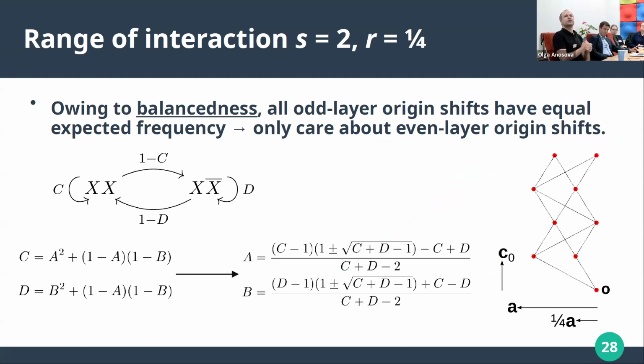And then just very shortly, if this parameter is 1/4, so your step is plus or minus 1/4, then it turns out that these things start to be homometric, for a very simple argument. In every second layer, you have minus 1/4 or plus 1/4, but the Markov chain is symmetric, so this must have probability 1/2.